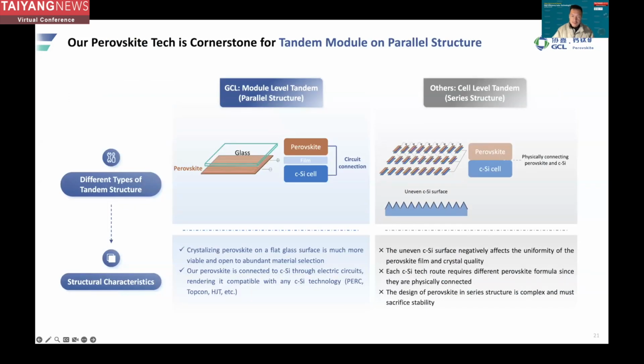And the problem is that because the surface of the silicon cell is not even, we know there is texture here. So if we need to fit the texture with perovskite, it's quite difficult. As we know, the texture is on the scale of a micron, but the thickness of perovskite is only hundreds of nanometers. So it's very difficult for perovskite to fit in all these textures. And also, each crystalline silicon technology requires a different perovskite formula because they are physically connected. And the design of perovskite in series structure is complex, and it will sacrifice stability, as we know here.